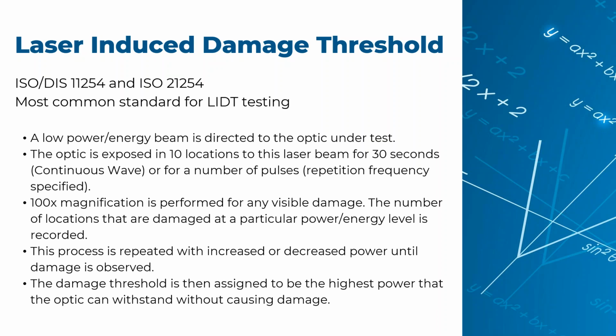All right. So there is a more technical specification, and this does not fall in for a lot of optics, but it's laser-induced damage threshold testing. One of the most common specifications we see is ISO DIS 11254 and 21254. So essentially, laser damage is you're going to take a low power energy beam and you're going to direct it at the optic. The beam is going to pulse on the optic at 10 different locations for 30 seconds. And that will be for a continuous wave laser. So the number of pulses and the repetition frequency, that's all something that you would work out with your coating supplier and your designer prior to testing the optic.